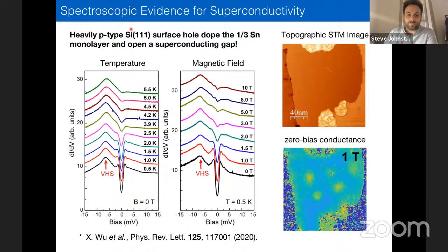So this is now data taken on the most heavily doped silicon substrates, where we have the largest amount of hole doping occurring in the tin monolayers. What's shown here is the densities of states zoomed in within the first 15 meV of the Fermi energy as a function of temperature. So at 5 to about 4 Kelvin, you don't see much going on here, right? This is to remind you, this is about where Hano's STM ends in temperature. There's a Van Hove singularity sitting here, which we can link directly to a Van Hove singularity in the non-interacting bands. And there's maybe some evidence of some sort of zero bias anomaly, but it's very, very weak.